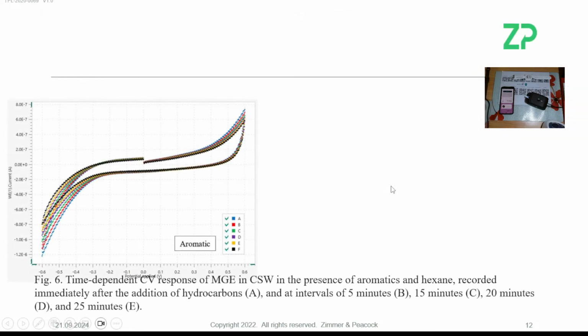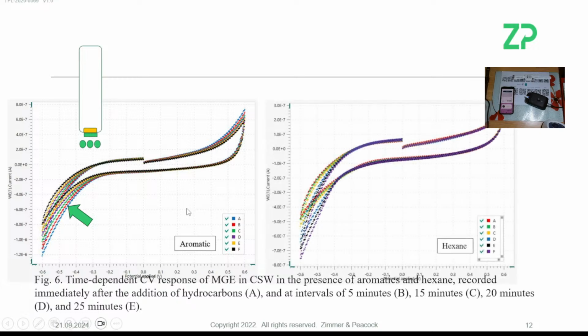Now let's go to your modified gold electrode. With your modified gold electrode, you have your oxygen reduction, and that actually decreases with time. I've got a suspicion that you are probably dissolving your material. I've got a super suspicion. But in fact, the aromatic compound is sticking to the surface. So with the aromatic compound, you lose signal of oxygen with time because the aromatic compound is sticking to the surface, like I was showing earlier on.